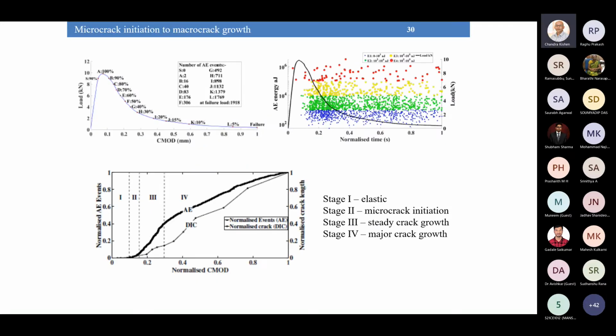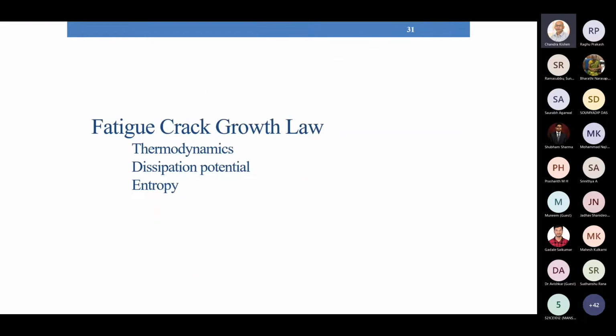And then the third stage is the steady crack growth stage. So we can see the rate of crack growth on the surface as well as the rate at which the micro cracks grow. The slopes are almost similar. And then the final stage where the major crack grows and leads to failure. So these could be clearly identified from this experiment. Those are about the experimental results.